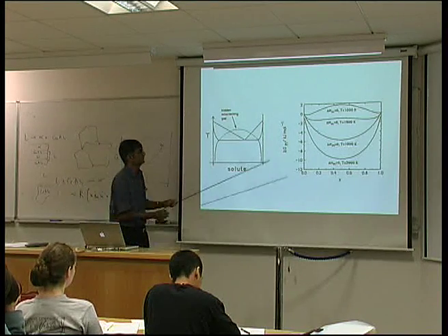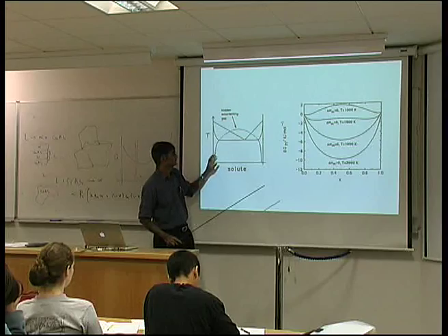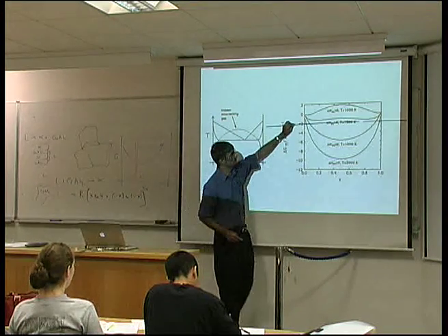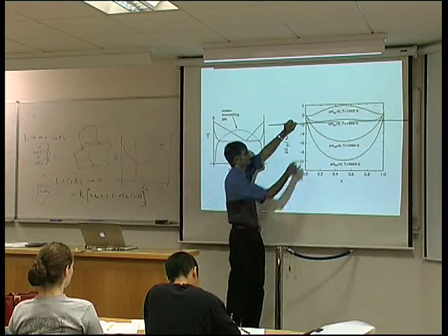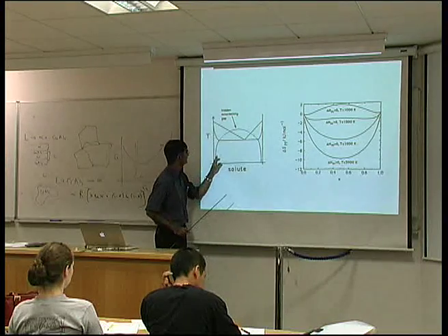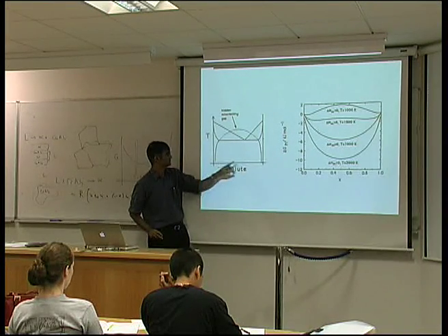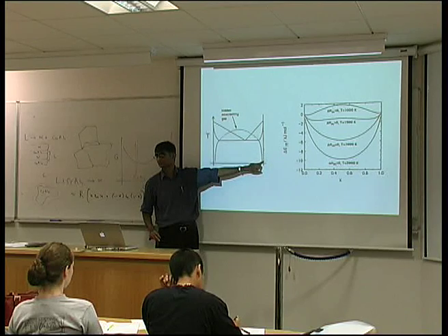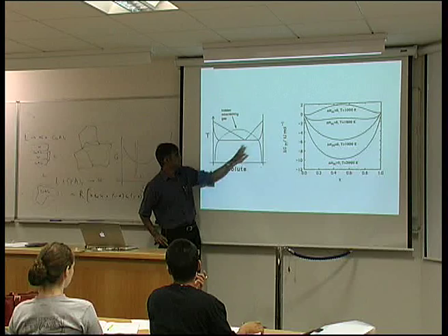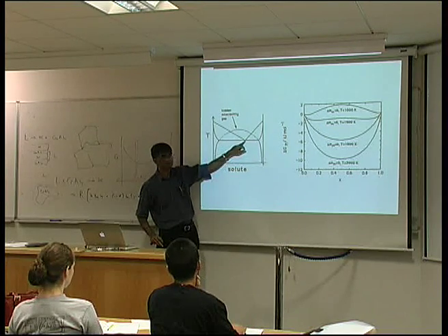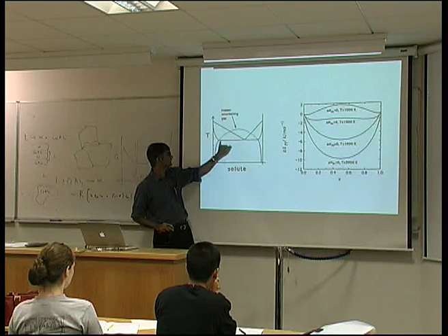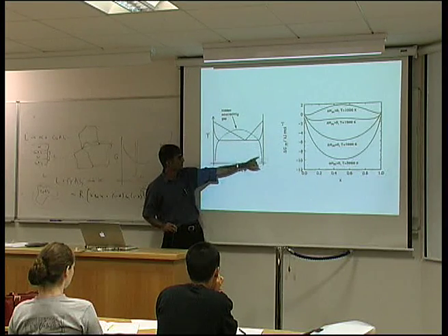Now, in order to plot a system where we have the clustering of like atoms, I can draw a common tangent to this curve and find the aluminium-rich and the copper-rich regions. So here, for example, are the aluminium-rich and copper-rich phase boundaries. Now, of course, this curve is interrupted by the formation of that eutectic reaction, but supposing we didn't have melting and we didn't have the eutectic reaction, then you would end up with a shape like this.